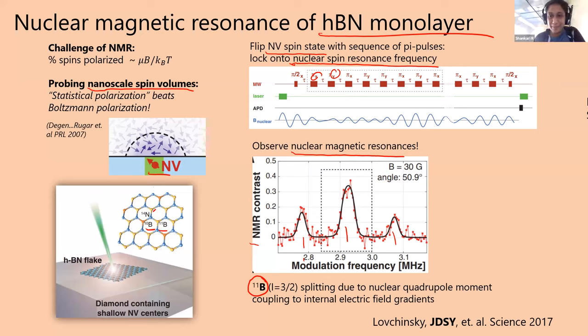Yeah, thanks. I also have a question. Yeah, please. There is a hydrogen on the surface of diamond, which also has a nuclear spin. How can you remove that effect from the experiment? We don't remove it. It's always there. But that's the beauty of spectroscopy: you can choose which frequency you look at. There's definitely a hydrogen signal, but the frequency at which the proton from the hydrogen has a spin transition is very different than the boron. So by looking at different frequencies, we can see it. And in fact, we actually see that there is a layer of something that has hydrogen in it that's between the boron nitride and the diamond.